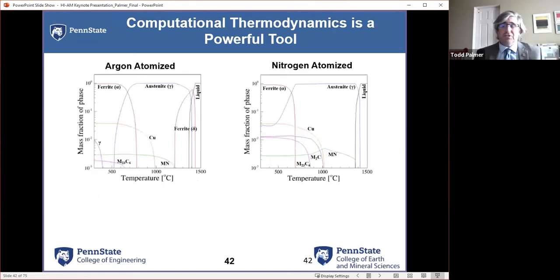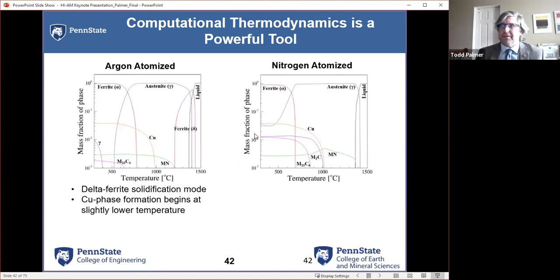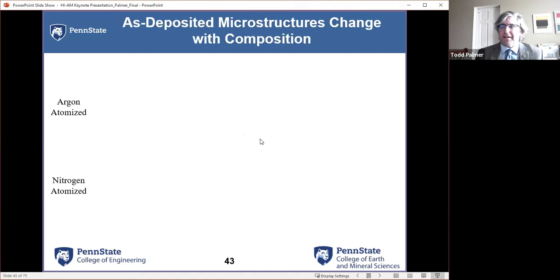Now, if we look at computational thermodynamics and just pull out Thermo-Calc, running some pretty straightforward calculations, we find that the argon atomized actually has a delta ferrite forming out of the liquid. You can see remnants of this in the as deposited materials. In the nitrogen atomized, it solidifies as austenite. So we have completely different microstructures that form. Copper phase is at a little lower temperature. What we start to see is our carbides and our nitrides are starting to impact here as well. The other thing to look at is there is thermodynamically a small amount of austenite that could be stable even down to low temperatures, whereas we see it basically disappears in the argon atomized materials.